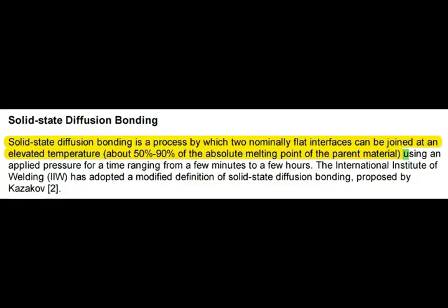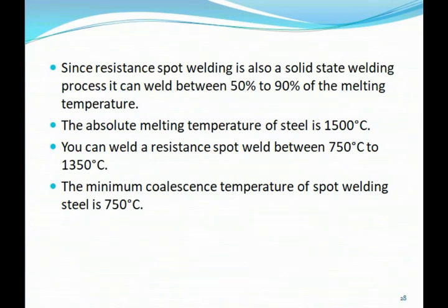Solid-state diffusion bonding is a process by which two nominally flat interfaces can be joined at an elevated temperature, about 50% to 90% of the absolute melting point of the parent material. Since resistance spot welding is also a solid-state welding process, it can also weld between 50% to 90% of the melting temperature. The absolute melting temperature of steel is 1500 degrees Celsius. You can weld a resistance spot weld between 750 degrees Celsius and 1350 degrees Celsius. The minimum coalescence temperature of spot welding steel is 750 degrees Celsius.